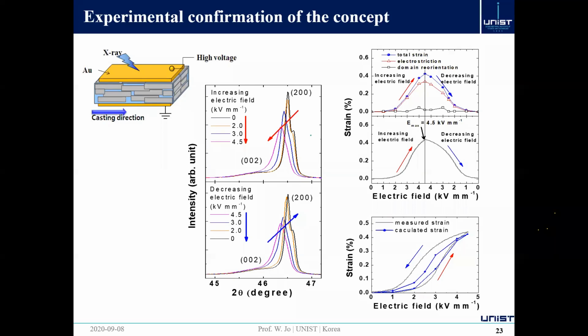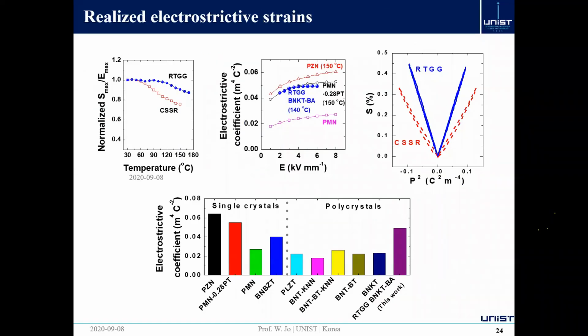This demonstrates the mechanism involved in this material. As you can see here, this is not typical ferroelectric domain switching, but electrostriction. The lattice parameter changes during the application of the electric field, which is completely reversible. So it comes back, and this gives the really high strain, just like I showed you here. Finally, this is a summary of the properties we achieved. You see that our newly developed material has a much better temperature dependence in its functional property, Smax/Emax, and this is truly electrostrictive behavior, which means temperature stability is better, and the response time is really nice. And we have already transferred this knowledge to industry, which is developing haptic devices out of this new material at the moment.